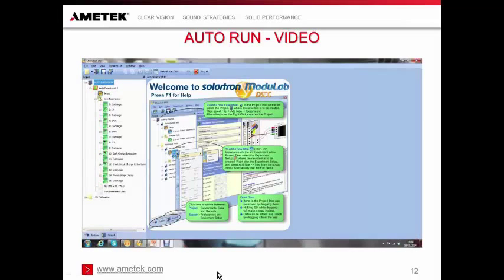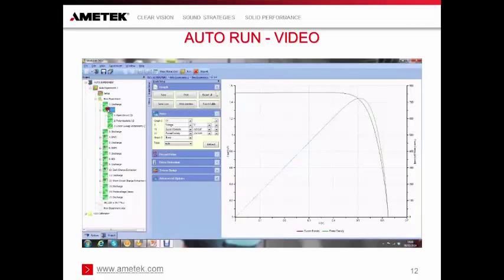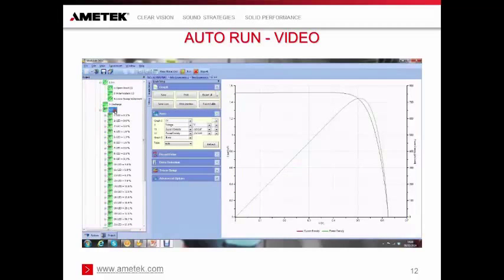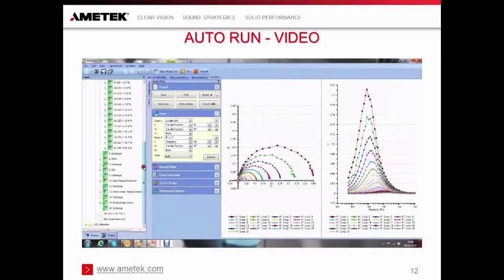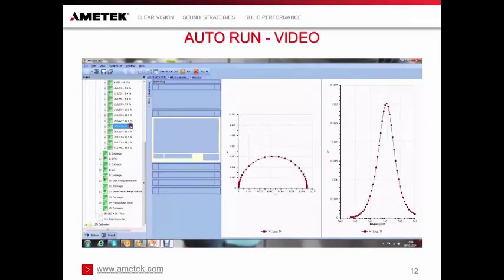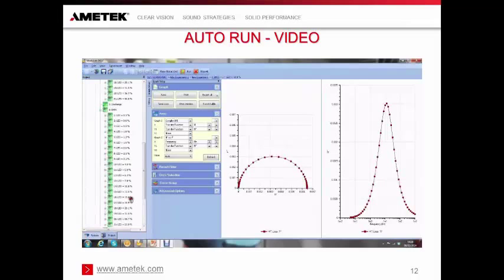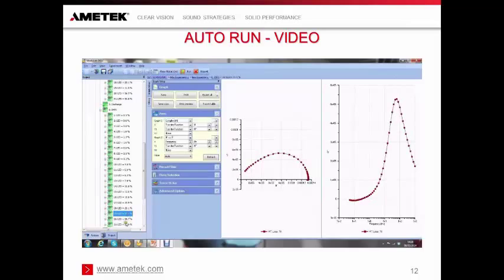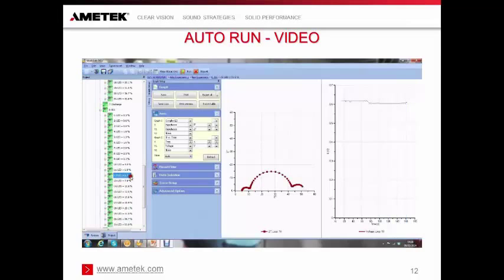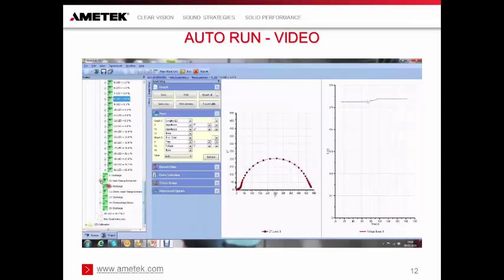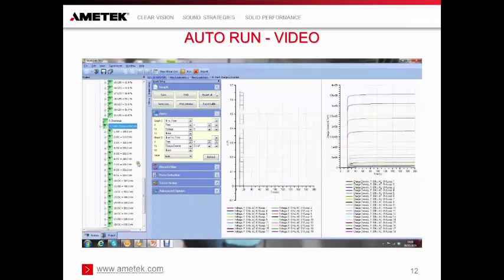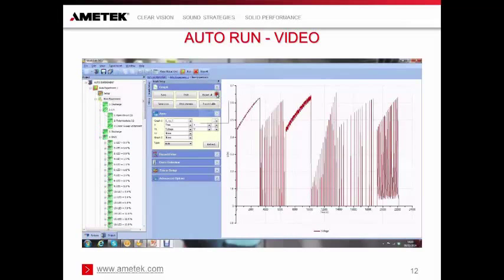So what we can see here is that we have a wide range of data generated, including the IV curve for the cell, the IMVS as a function of light intensity. These are different light intensities being shown. The IMPS as a function of light intensity. Once again, this is fully automated, therefore the user does not need to be present during these experiments. Impedance spectroscopy as a function of light intensity. Notice how the impedance spectrum changes markedly as we change the light intensity. And here are some examples of charge extraction as a function of drive voltage. So that's the data file that's created automatically. Once you've got the data file, you simply press Export to Excel, and Excel will automatically open.